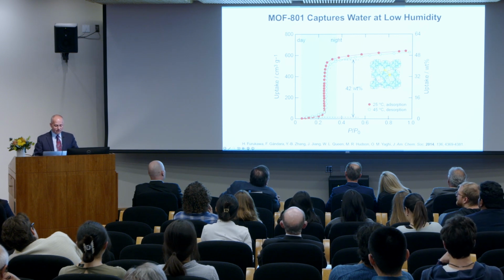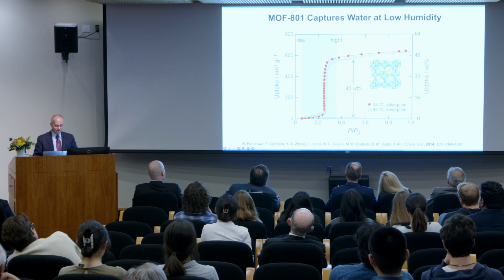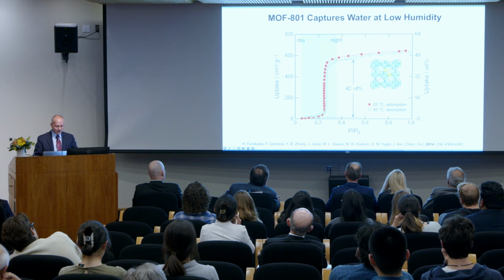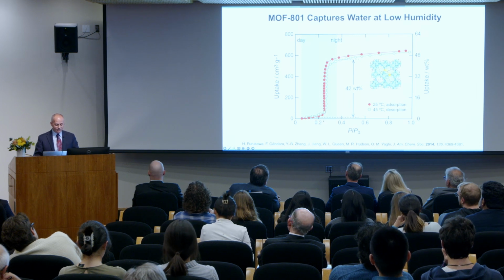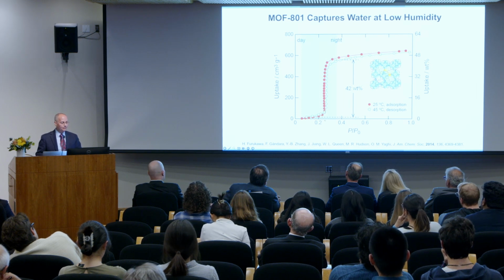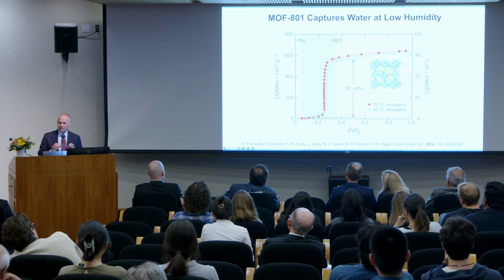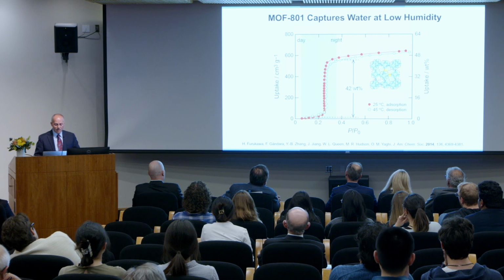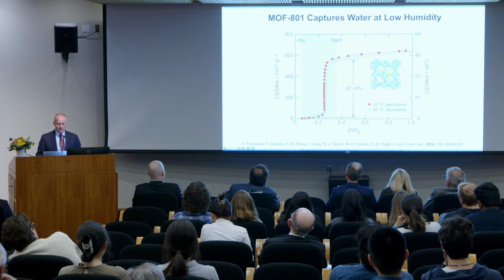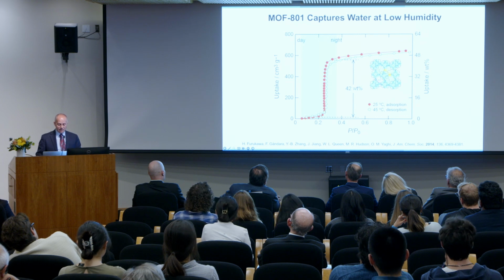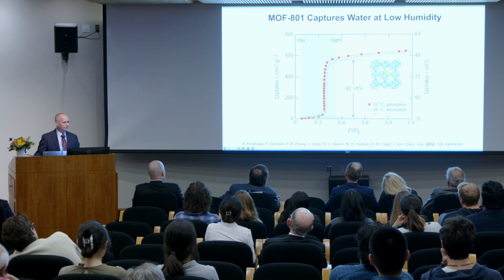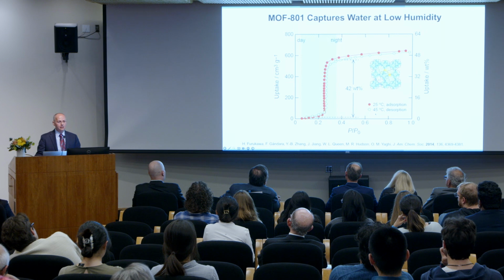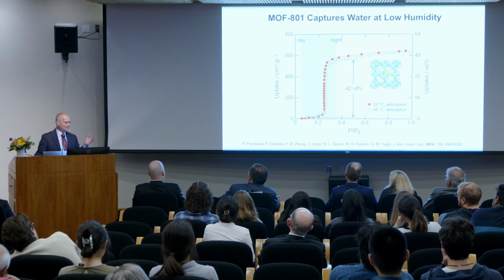And so we were taking these measurements with water, and we get the red line. And when I looked at the red line, I was almost floored because it's taking up water at very low humidity, around 20% relative humidity. But what was more amazing is that you can take the water out, in the green, at 45 degrees Celsius. Okay? Well, that's nothing. That's sunlight, especially in the desert.